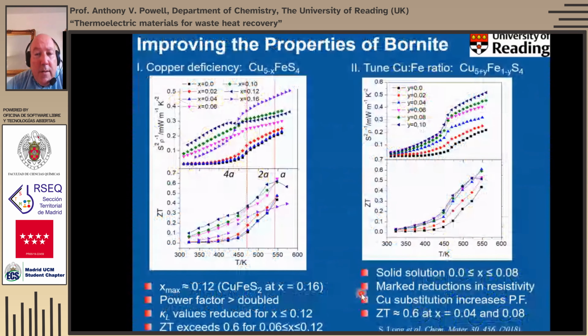So I'm going to go through this fairly quickly. We've done 2 different things here. We've used copper deficiency, so we've made some copper vacancies. So again, a similar strategy that has to oxidize some of the remaining copper to maintain charge balance. It introduces some additional holes. We do get some significant improvement in the electrical properties. The power factor is more than doubled. The thermal conductivity is also slightly reduced, but the main impact is on the electrical properties, which is what we were targeting. And we can get a ZT that exceeds 0.6 in that material.